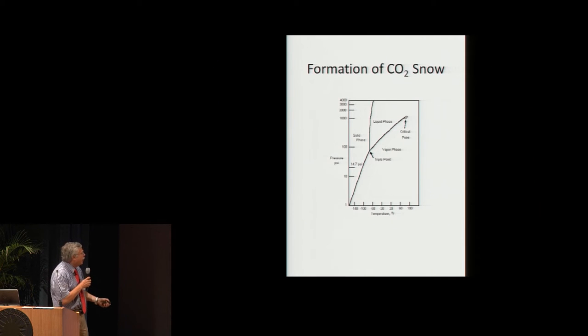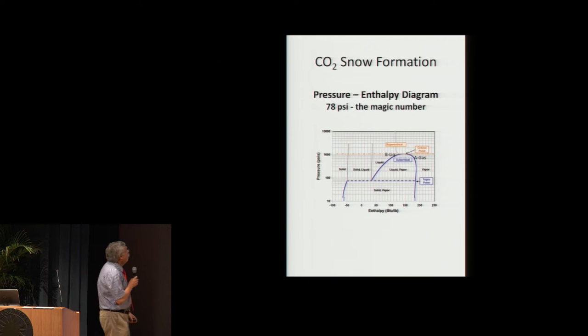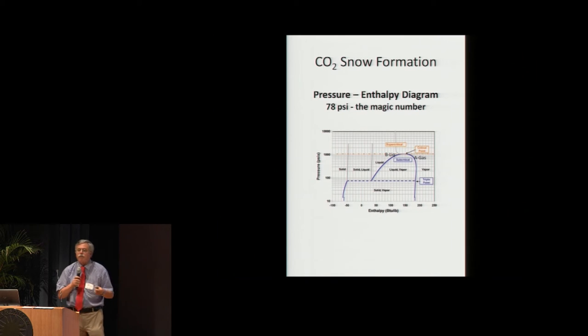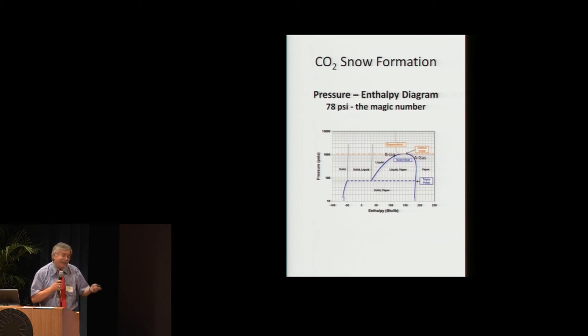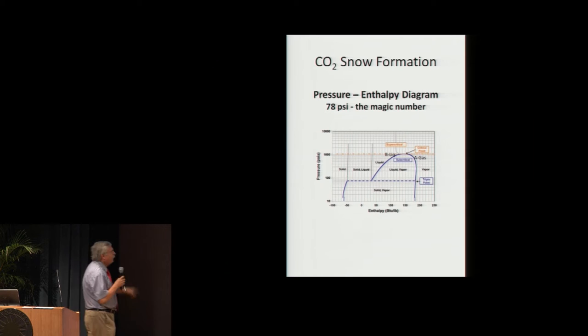So to gain a better understanding, we go to a little chemistry. Pressure enthalpy diagram. So for those not familiar with enthalpy, it's kind of like entropy, energy, but it's essentially a measurement of a quantity of interest to chemists. There's 2 points of interest on this. If you're taking liquid CO2 in the cylinder, and you pass it through a nozzle, what was a line on the previous diagram becomes a 2-phase region of mixed vapor and liquid.